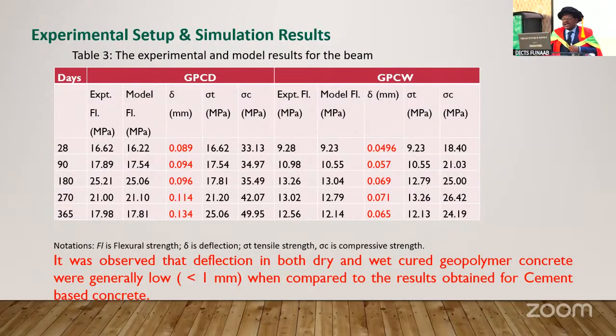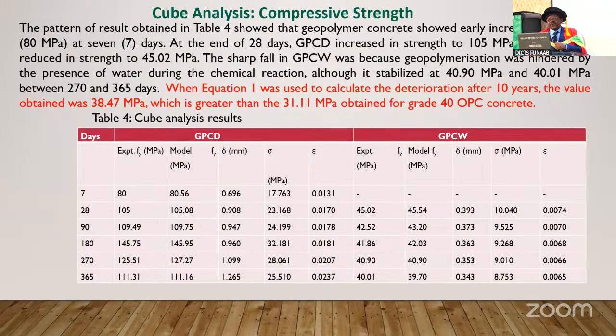Now, we look at the cube analysis. The pattern of result obtained in table 4 showed that geopolymer concrete showed an early increase in strength of 80 MPa at 7 days. At the end of 28 days, the GPCD increased in strength to 105 MPa, while GPCW reduced in strength to 45.02 MPa. The sharp fall in GPCW was because of the geopolymerization, which was hindered by the presence of water during the chemical reaction, although it stabilized at 40.90 to 40.01 MPa between 270 and 365 days.